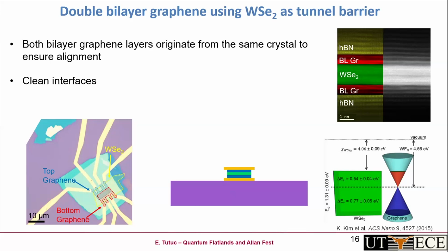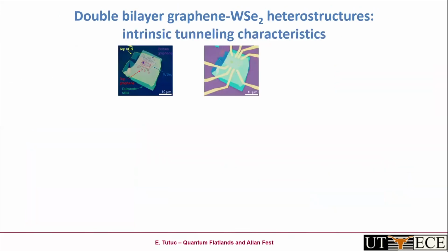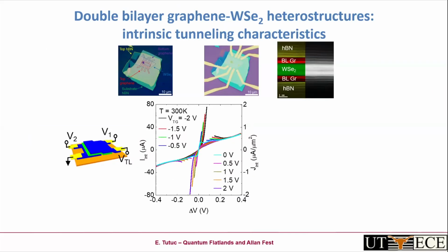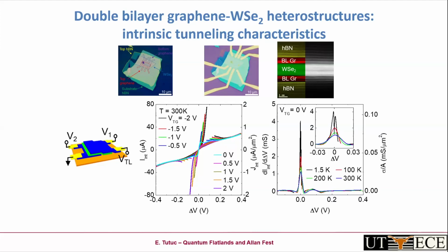So let's do this tunneling measurement that would tell us, on one hand, if we have twist control, and then what we learn about the sample. Okay, this tunneling measurement is going to be a 4-point measurement, and it shows textbook gate-tunable negative differential resistance at room temperature. Very nice resonant tunneling, so it's good. Twist control is present here. It ensures momentum conservation in tunneling, okay?